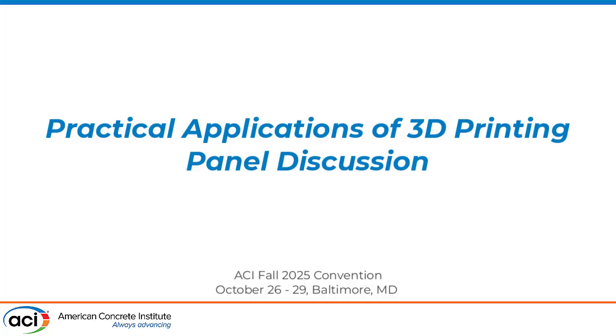So we did a mini study on the side on how we should control that. Because if you just let it sit out in the air, it really depends on the print. If you do one of those big blocky dragon's teeth, it's not too bad. But if you're doing the wall sections, a lot of shrinkage cracking is what we saw. So we just air cure, ambient, whatever.